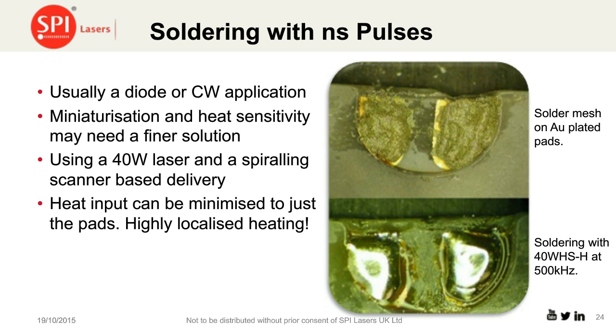Other applications, such as soldering, you wouldn't traditionally think of fiber lasers as the source of choice. Again, usually it's diode lasers. However, one of the things we're seeing in today's society is miniaturization and heat sensitivity, and this may require a finer solution than is offered by some of the other technologies. Here is an example where a client was looking for minimal heat input into a very sensitive PCB component, where they needed to minimize the local heating. Even a CW laser was putting in too much heat and damaging parts close by.